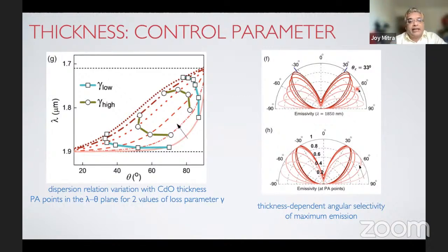Okay, and this is the dispersion plot. I'm not going into the details of it, but we can see these points here which show perfect absorption, and it is easily tunable by 2 parameters, either the loss in the system, affecting epsilon double prime, or by changing the thickness of the thin films themselves.